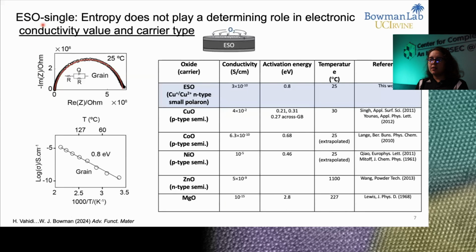First, I want to show you that I'm looking at the conductivity using electrochemical impedance spectroscopy. And first, we're looking at the single phase material to get that out of the way. We're looking at this EIS spectrum, the Nyquist plot of the single phase data, and you are looking at this conductivity semicircle that we have fit with an R-RQ equivalent circuit model at room temperature, and we repeat this at various different temperatures to calculate the activation energy. And the conductivity as a function of temperature is plotted over here. Activation energy is around 0.8 electron volts.